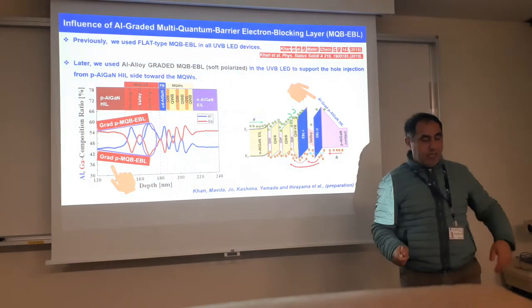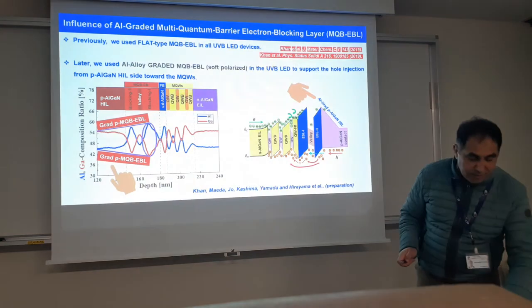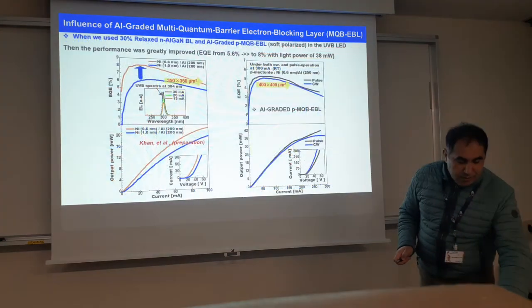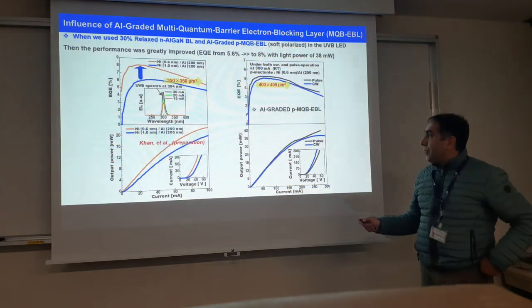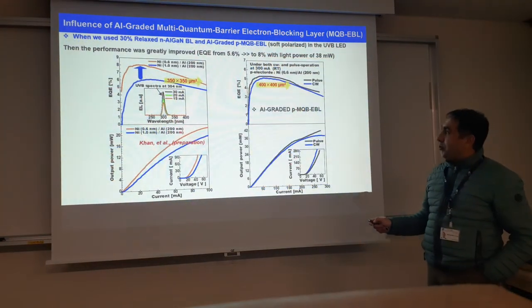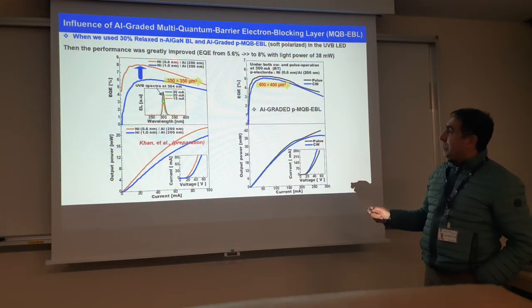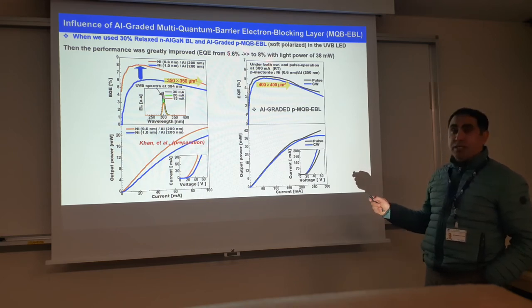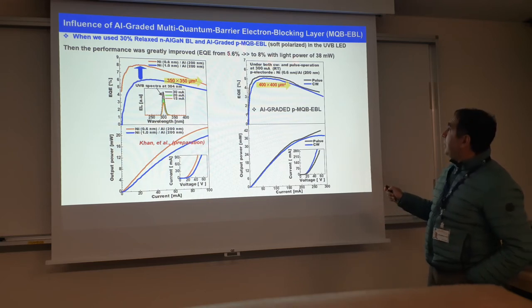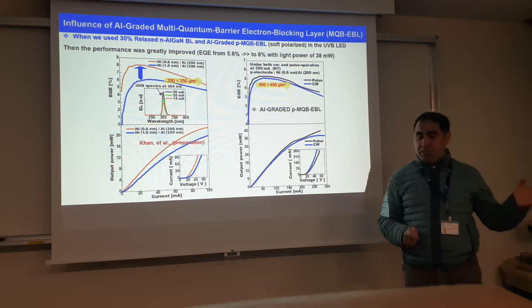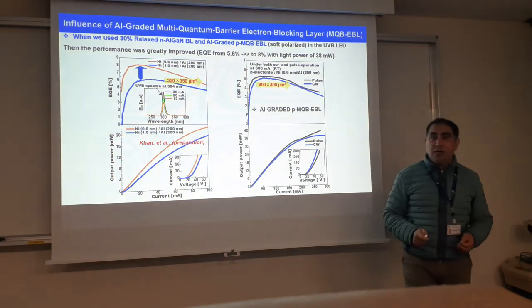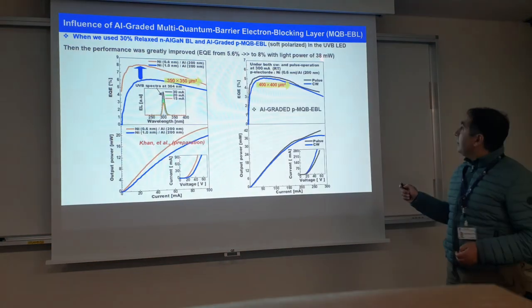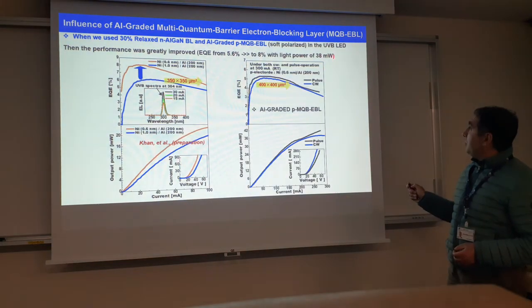With this new architecture, we tried to make an LED device. We improved our EQE from 5.6% to 8% with a light output power of 38 milliwatts — previously it was 17 milliwatts.